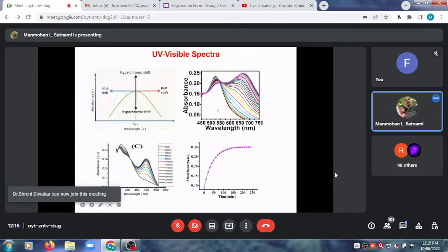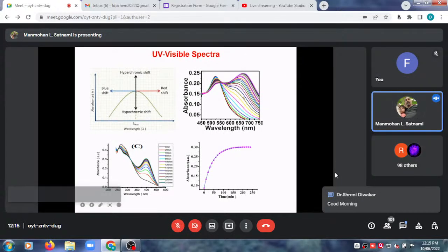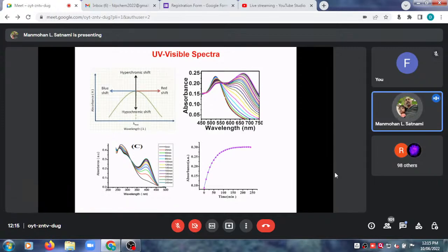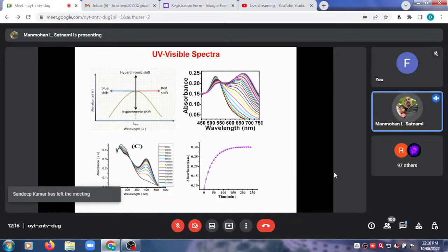Okay, then let me add sodium chloride to the gold nanoparticle, then aggregation will start and it will give a spectrum with maximum at around 650 or 655. So what is happening? The concentration of gold nanoparticle is decreasing. Therefore, the absorbance at 520 nanometer is decreasing. And at the same time, the absorbance at 655 nanometer is increasing. What does it indicate?